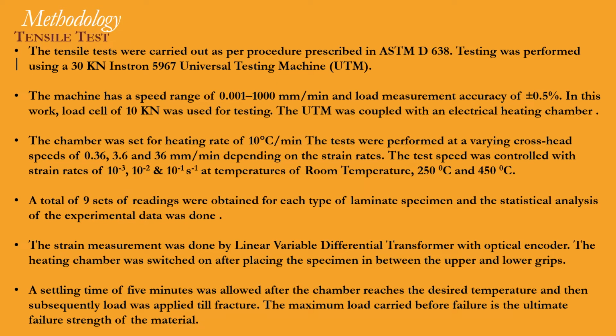Methodology. Tensile test. The tensile tests were carried out as per procedure prescribed in ASTM D638. Testing was performed using a 30 kN Instron 5967 universal testing machine. The machine has a speed range of 0.001 to 1000 mm per minute and load measurement accuracy of plus or minus 0.5%. In this work, load cell of 10 kN was used for testing. The UTM was coupled with an electrical heating chamber.